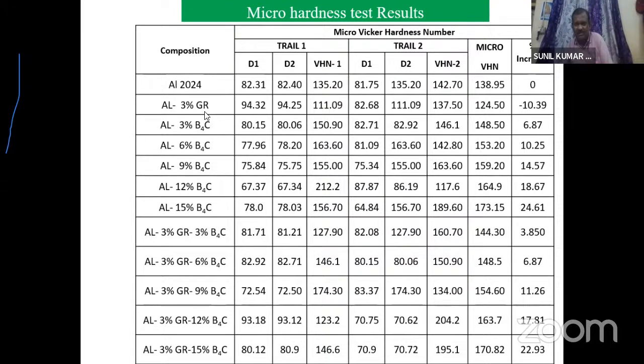Similarly, aluminum 3% graphite: trial 1, 111.09, trial 2, 137.5. So this is the total micro Vickers hardness number. Then this is the increased value. Then aluminum 3% B4C, these are the values obtained. For aluminum 6% B4C, these values are obtained, and so on.